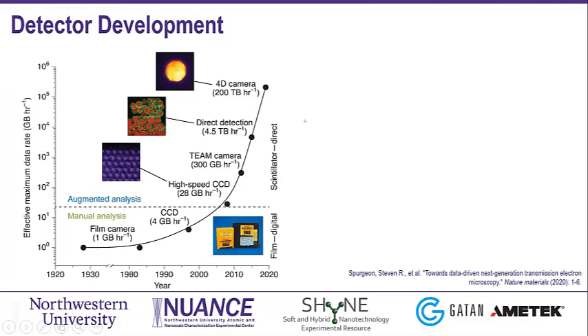As I mentioned before, over the past years there has been a very rapid evolution in terms of detection, and that really propelled the usage and the application of 4D STEM here. Some of you might be familiar with this. This is how we used to collect images and diffraction patterns in the microscope, using film cameras. And this is a nice chart put together recently in a review here. Using film cameras, you basically collect 1 gigabyte per hour at the most. And on top of that, you have to learn a new skill, how to develop those films, right? With the CCD, there was already an increase of about 4 times in data collection, and then it really exploded after the insertion of direct detectors and high-speed cameras here.